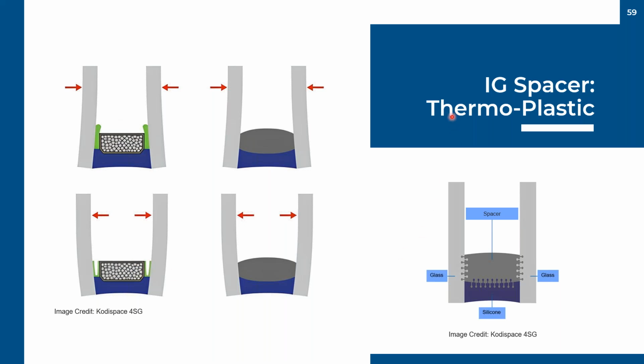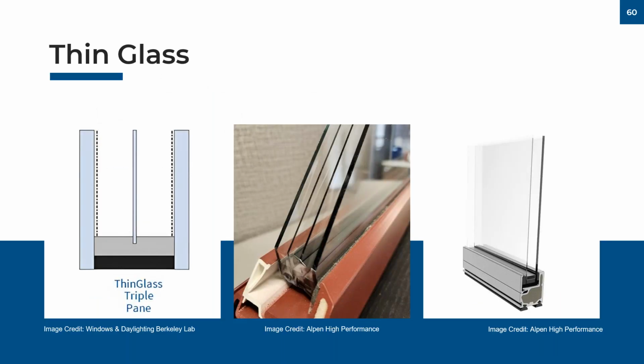And that's what you'd find with a thermoplastic spacer, or TPS, as it's sometimes known in the industry. It takes a different approach. Rather than this multi-point system right here, it injects more of a structural sealant as the primary seal and backs it up with a secondary sealant behind there. And that TPS spacer also chemically bonds to the glass itself and the secondary spacer, producing a very long-lasting seal, adding more life to our windows and doors. Thermally, this performs basically the same as the warm edge spacer that we saw in the previous slides.